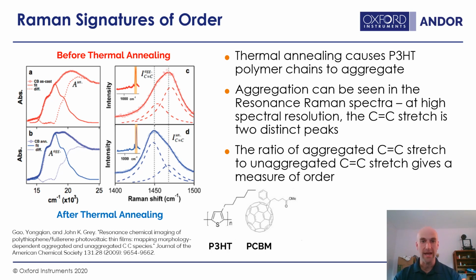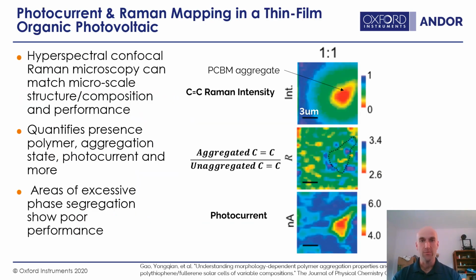And the really interesting part is that we can use this spectroscopic metric of order or of aggregation to compare with the actual photocurrent generated in a functioning solar cell. So hyperspectral confocal resonance Raman microscopy can match microscale structure and composition to performance, if you have the equipment suitable for both measuring the spectra on a confocal scale as well as measuring the nanoamps of current that you're generating with the light that you're using to generate the spectra.